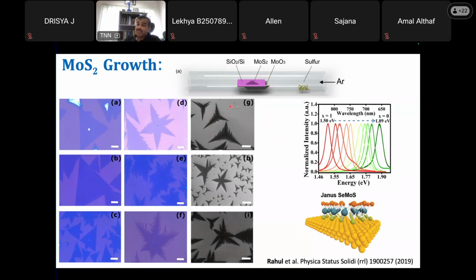Not only that, some of the sulfur can be replaced with selenium in a very selective manner. Molybdenum selenide, where sulfur is completely replaced with selenium, is again a semiconductor with a band gap of 1.5 electron volt, but molybdenum disulfide has around 1.89 electron volt. So we showed that you can control the band gap in a very controllable manner, in the monolayer limit, that you also need to think about. From sulfide to selenide, you can have a variety of monolayer semiconductors in this fashion.